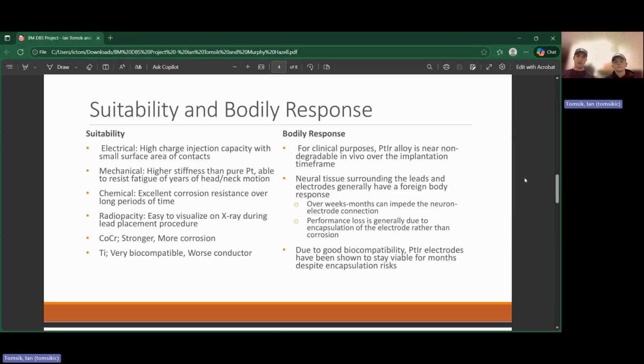For suitability, electrically, it has a high charge injection capacity due to the platinum and a small surface area for the contacts due to its high charge injection capacity. Mechanically, it has higher stiffness than pure platinum, and it's able to resist fatigue for a number of years of head and neck motion. Chemically, as I said before, it has an excellent corrosion resistance over long periods of time, and it shows up very well on X-rays.